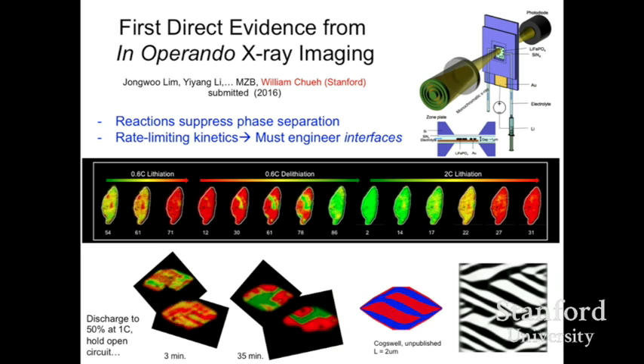in situ during battery operation. And there's a number of different techniques that they've used. What I'll just focus on is some recent results from a paper that we've recently submitted, where there's basically a microfluidic liquid cell with a transparent electrode, and you have individual lithium iron phosphate nanoparticles sitting on the electrode, and you can literally see them as they're transforming using also X-ray methods, so you can detect where is the lithium basically. So these color images are telling you where the lithium is.